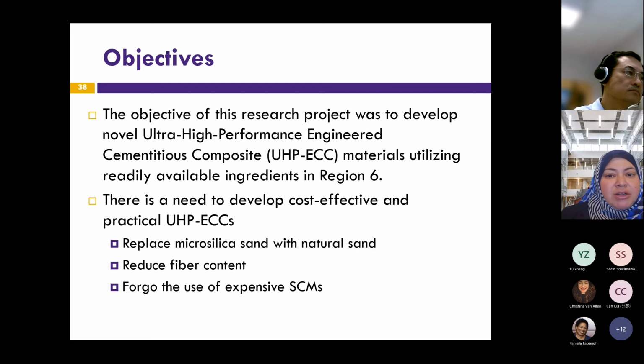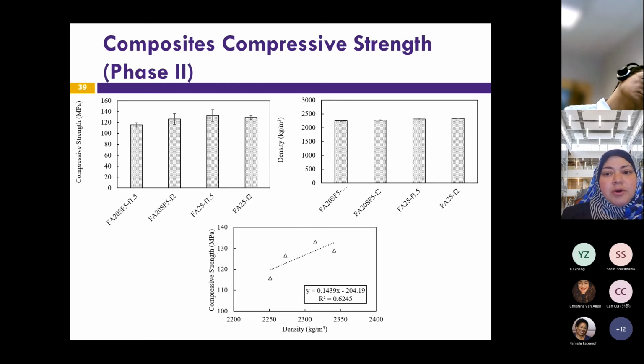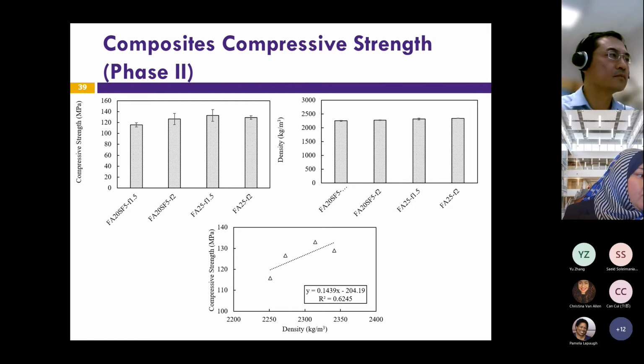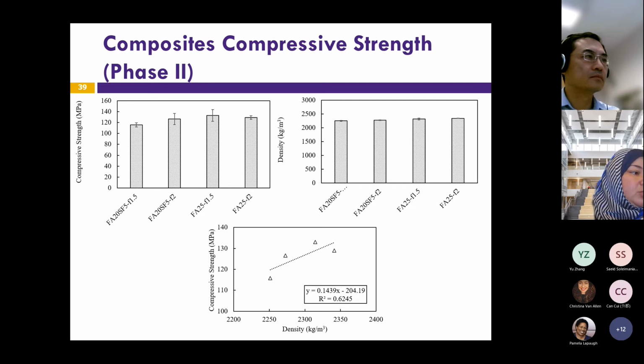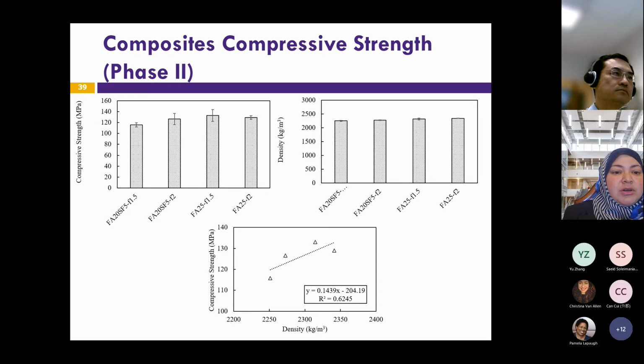Okay, and we did so many trials. I'm showing you the successful part of the matrix after 8 months of work. But this slide here shows 4 mixes that were very successful. They all exhibited a compressive strength higher than 120 megapascal with low fiber content without affecting the ECC performance. So as you can see here, we have 1.5% and 2% fiber content. We have no silica fumes. The best performing one right here has no silica fumes and has 1.5% fiber content.